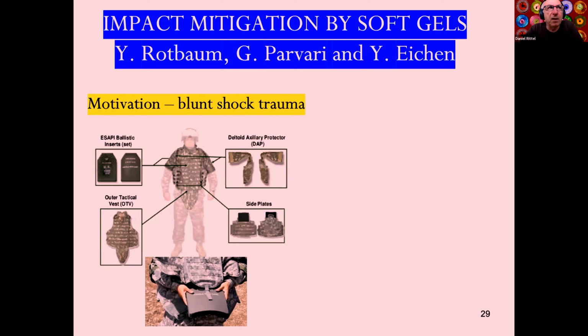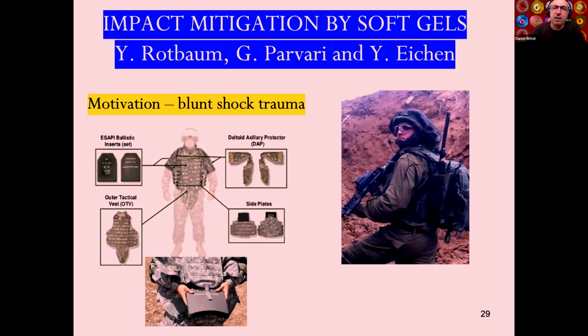And when you experience a shock, the first thing that propagates, and the fastest, is an elastic acceleration wave, and the damage and destruction of your protection comes much later. But at that stage, the brain, the liver, the heart have been violently accelerated. And it is not a boron carbide plate or an alumina plate that is going to protect you or your head against the shock. On the contrary, they're very good waveguides or wave propagators for elastic waves. And this is a typical fighter. By the way, this is my former student, Dr. Rotbaum, and that's his picture.